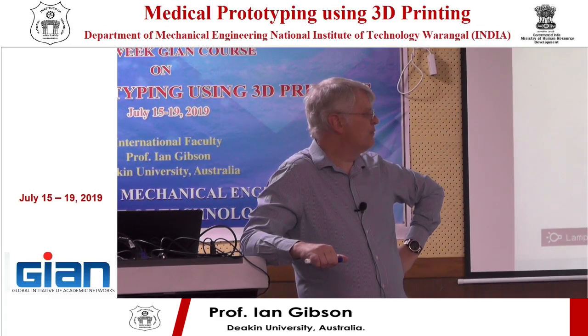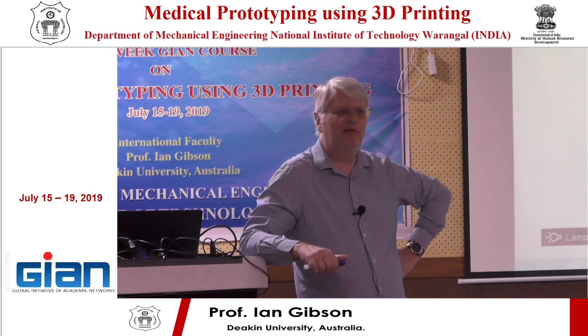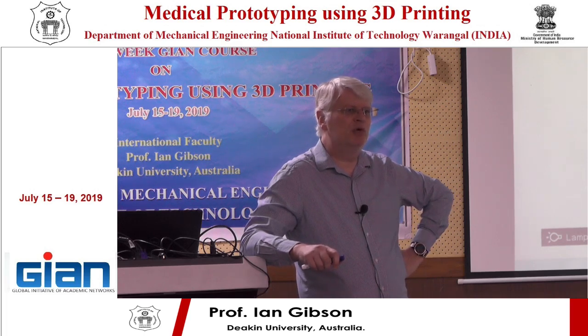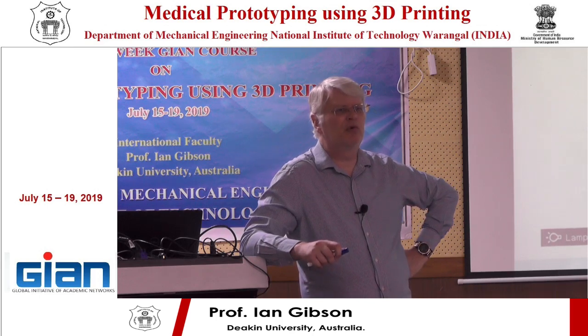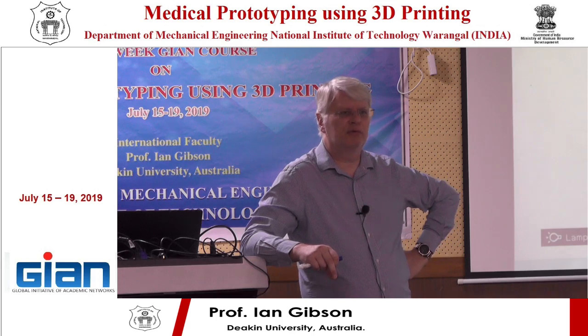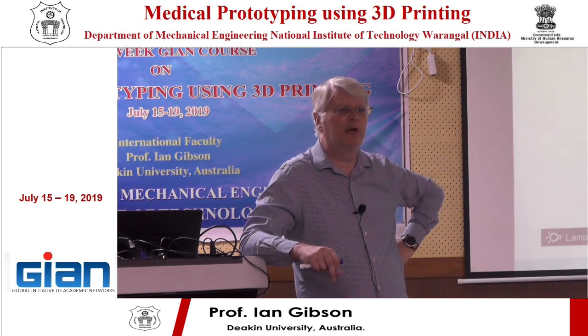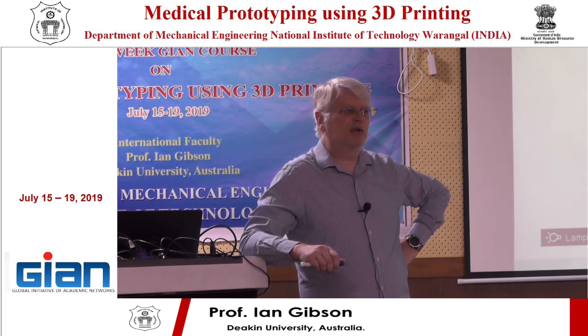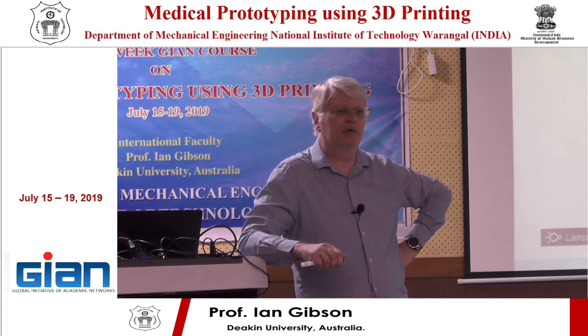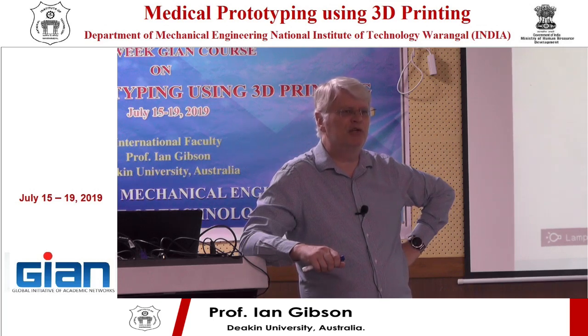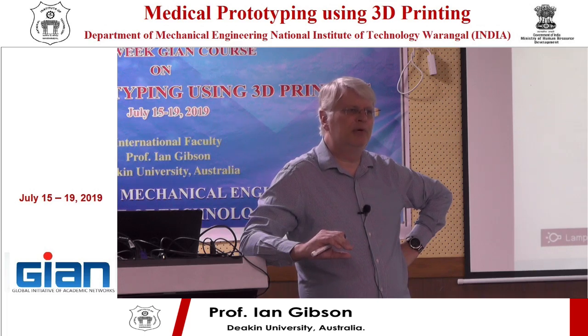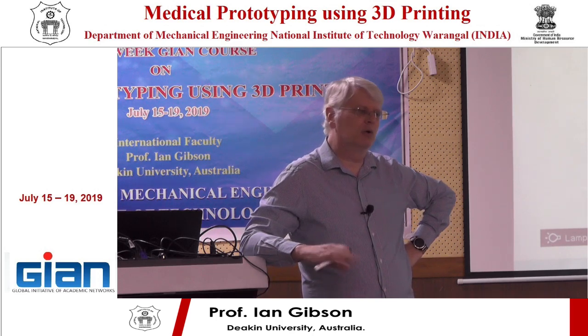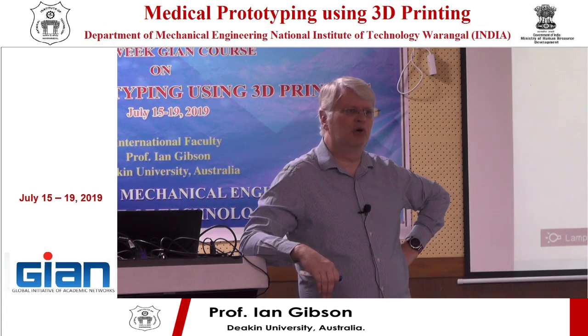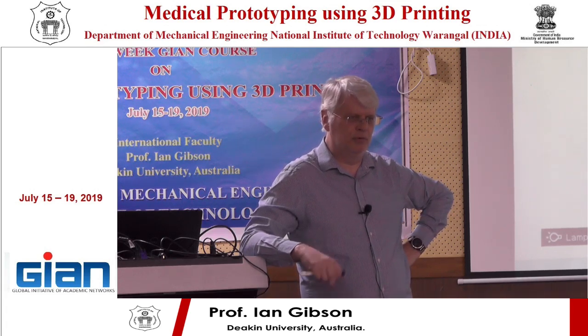What was I also going to say? We've not mentioned the pore sizes very much yet. The scaffolds that we used to generate, we try to aim for a pore geometry of around 500 microns, about half a millimeter, in general overall dimension. Bone cells are normally around 50 microns. And so that allows for a population of cells to occupy a pore, but without too much bridging across that pore. And then also a bit of space for nutrients to get there, to allow for the cells to join together and to become healthy.